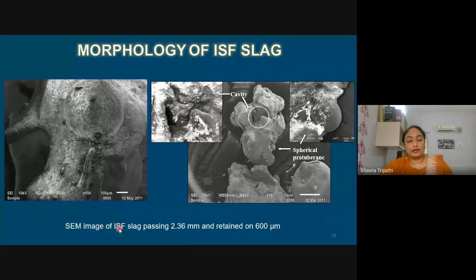This particular SEM image is of slag particles which are passing 2.36 mm and retained on 600 micron. Another picture on the right hand side shows that the slag surface has cavities. So why is it very important to study the morphology? Because in concrete, the particle shape and particle size have a very great influence.